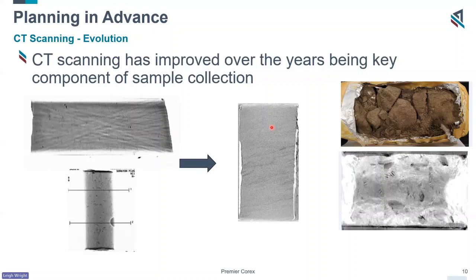Whereas you can see a more recent scan from 2024. Again, it's a preserved sample. These are the same length. And you can see this small, shaly, more clay-rich zones, a more homogeneous zone here, where you can then identify the bedding. In terms of formation damage and the SCAL, making sure that they're getting the best path of flow, it's extremely important. I mean, when you get these CT scans, you can look through them in 2D and 3D and see the different zones.